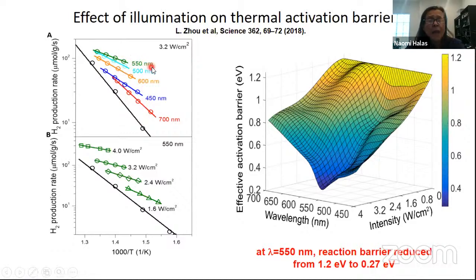I can, for example, take the wavelength that's the best, 550 nanometers. I can go back, measure the reaction in the dark, and then turn on just the light of that wavelength and measure it as a function of intensity. And as I increase the intensity, at each intensity, I do the reaction at 4 different temperatures and I measure the reaction barrier. Measure the reaction barrier, measure the reaction barrier. And so all this data now gives me the ability to plot out this really cool looking curve.